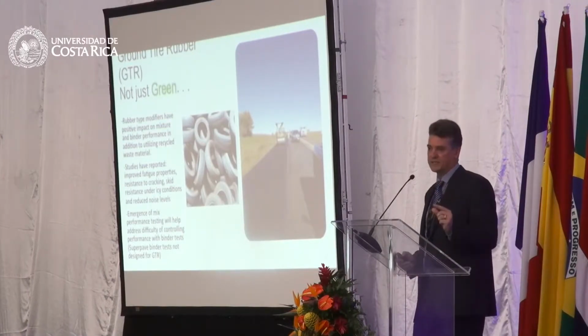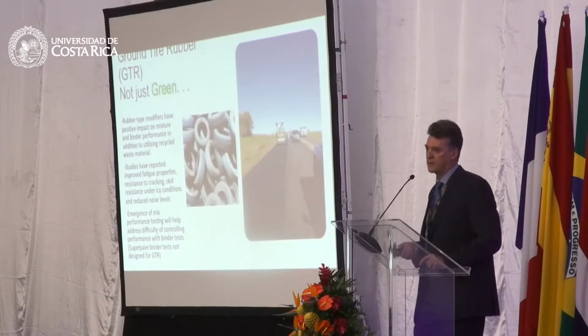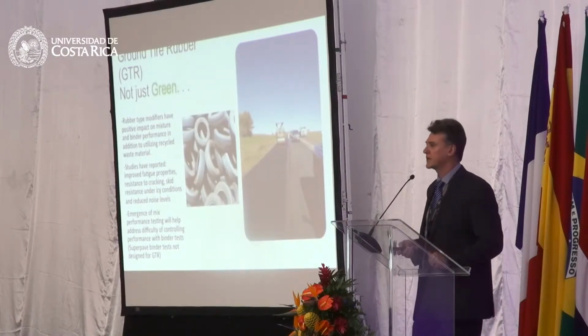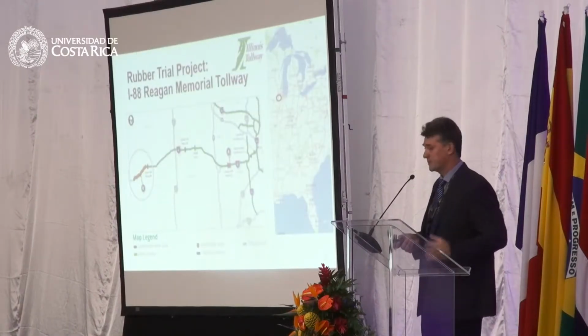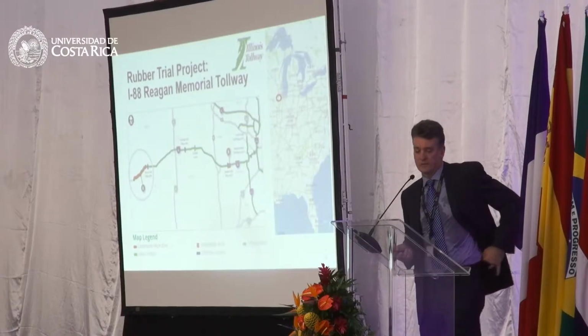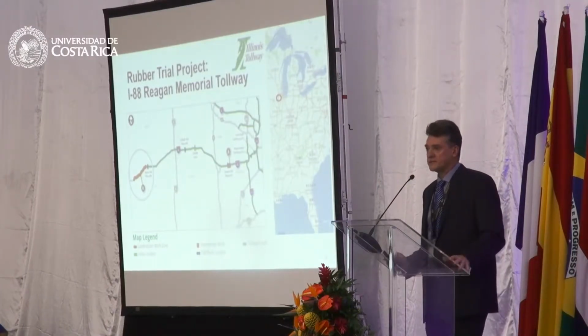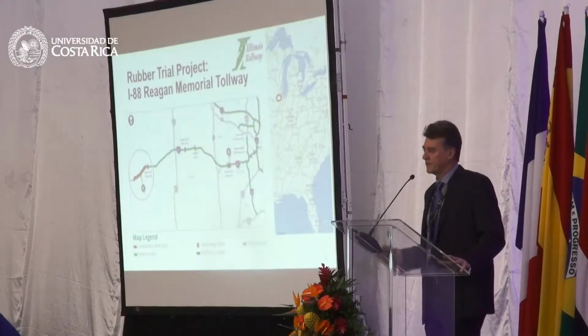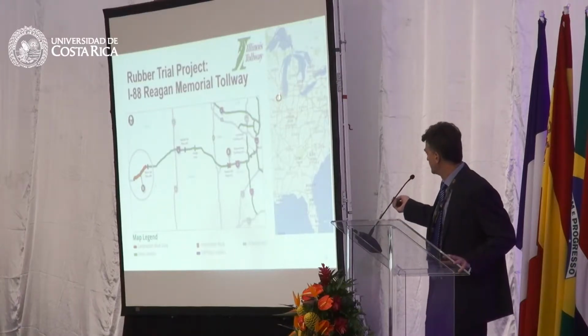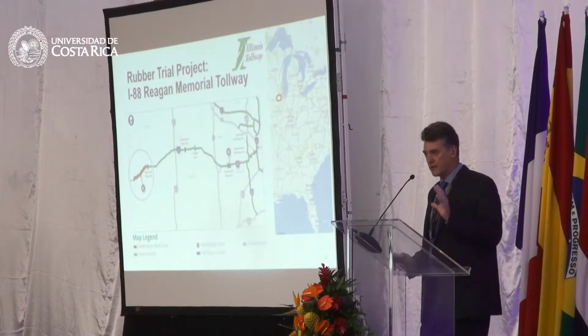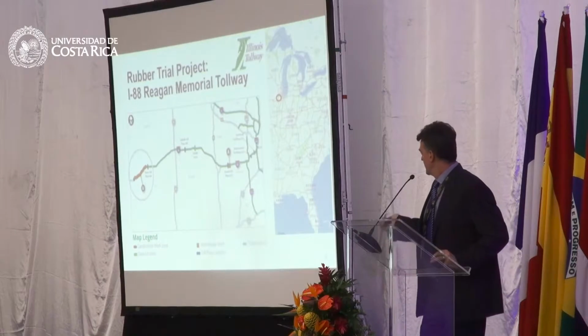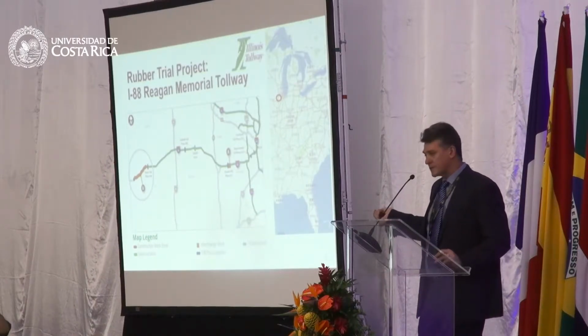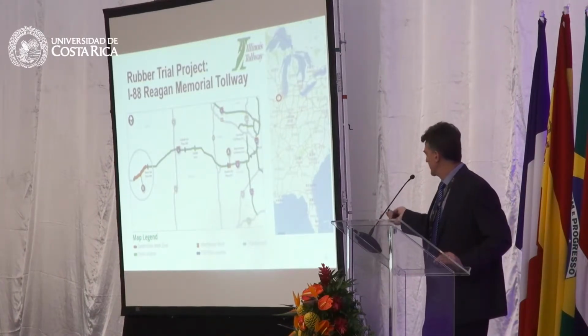We can see enhanced performance properties with ground tire rubber. It really does improve some of the characteristics of the mixes you'll see, and that should be a motivation beyond just recycling. So we put these to the test in a very high traffic environment near Chicago, Illinois, and this was on the tollway system and on a route Interstate 88, just west of the city.